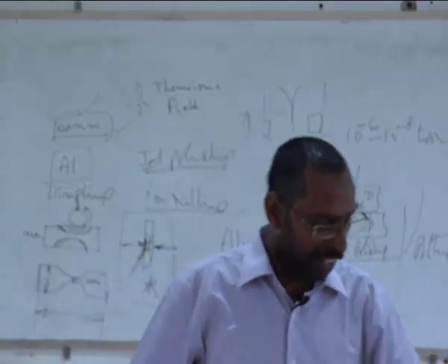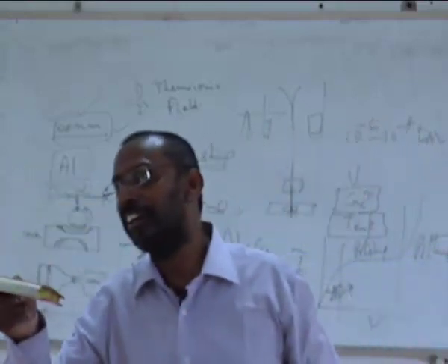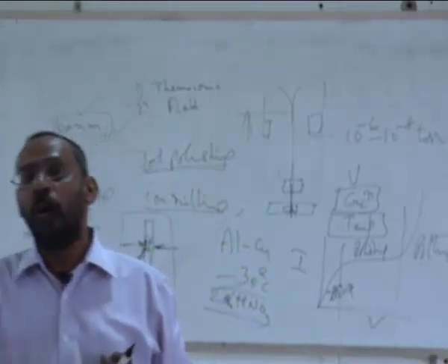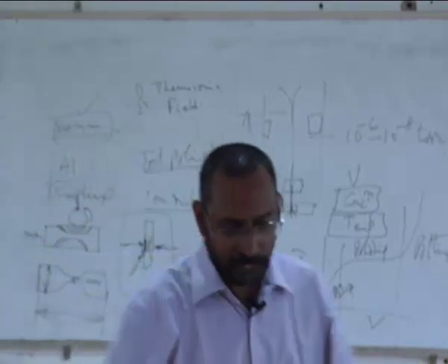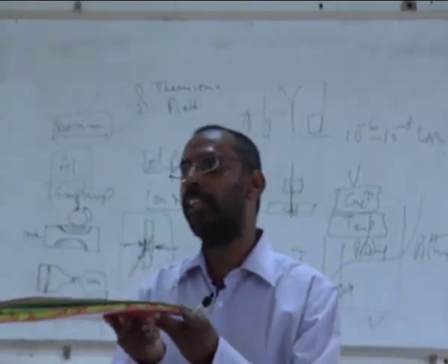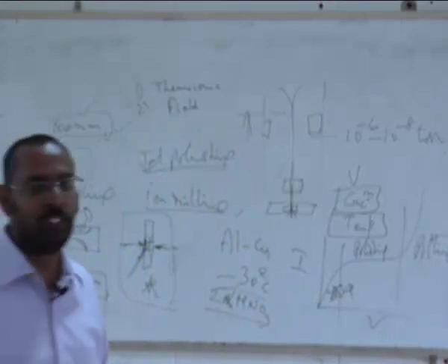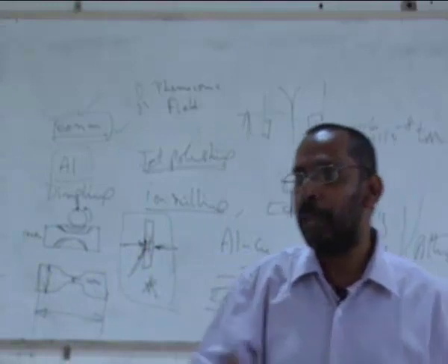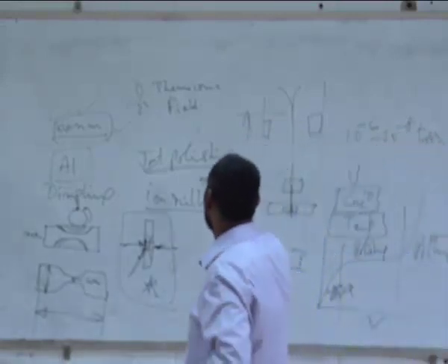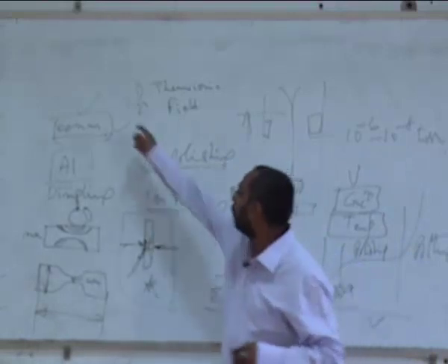So I am not seeing a big plate like this. I am actually seeing a small speck out of this plate. Let's say I have a rolled plate and I am taking only a speck out of it. How do I take that 3 millimeter disc? If I have a sheet like this formed by slicing a sample, in metallic samples I can use a punching machine. If you have ever seen papers being punched, a similar punch can be used to punch a 3 millimeter disc. And this disc is allowed to go through jet polishing, finally to end up into this.